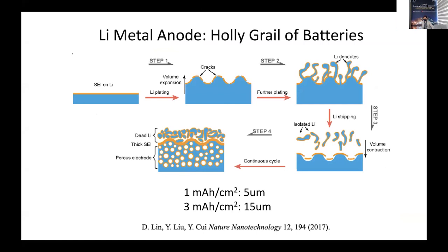And then at the interface, because of the solid electrolyte interphase right there, this plating cannot be guaranteed to be a flat plating layer by layer. You're going to cause a surface morphology change that will break the SEI. Once the SEI is broken, you will create a hotspot that will grow out metallic lithium dendrites and cause the battery shorting. And so this is a really, really challenging problem. Remember, if you need 3 milliamp hour per centimeter square capacity, which is common in a battery cell, it's 15 microns of lithium plating. And then when you do stripping during discharge, the 15 microns are gone. So for each layer of electrode, this 15 microns up and down is too much.